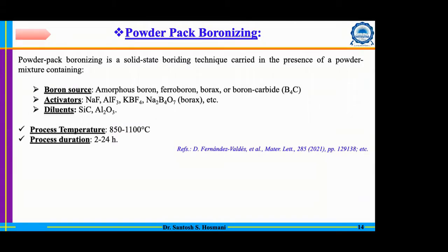However, the literature observed, and we also observed in our work, that especially at elevated temperature, SiC forms a sticky layer on the steel surface. And that sticky layer is difficult to remove easily. That means probably you have to do some kind of grit blasting or something to remove that sticky layer, and that may add some additional cost. That could happen whenever you are using a very high temperature, especially beyond 1000 degrees Celsius. Otherwise, this SiC has no role in any reaction as such.